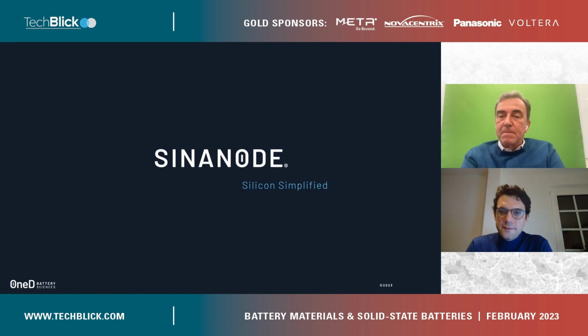Great. I guess one last question, and then we have to move on to the next presenter. The question is, what is the first cycle loss? So typically the nanowires have a 92% first cycle efficiency, 8% loss, which is about the same as graphite. And we do that regardless of the percent silicon. If you measure in actual cells with commercial cathode, anywhere from a few percent silicon to 20, 30% silicon, it's flat. So it's 90, 91, 92% first cycle efficiency, which is excellent and does not require any pre-lithiation.